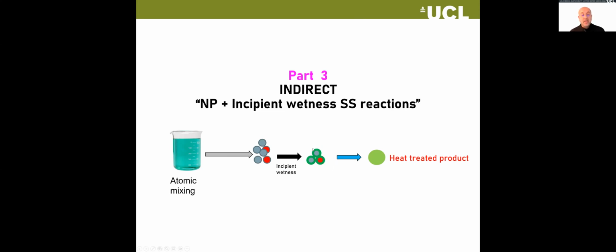And then we have the addition of some kind of lithium source. And you might say, why are you adding lithium here? And I'll save that for a question if somebody wants to really know. But we're adding something using incipient wetness. And incipient wetness is a process by which you are basically adding a liquid containing some other metal ions, like lithium hydroxide. You basically add the minimum volume of liquid you can to a certain given amount of powder. And the idea is that if you carefully dry that, the lithium hydroxide will be evenly mixed with your initial nanoprecipitate. I've shown it as a coating, and it is used for coatings as well. It's used for coating platinum onto catalyst supports, for example.